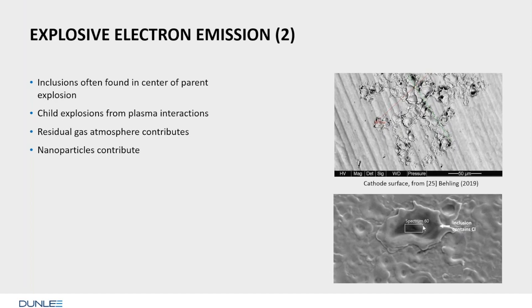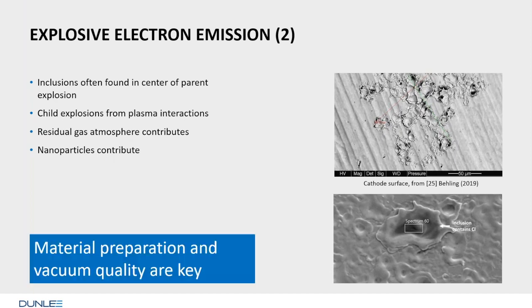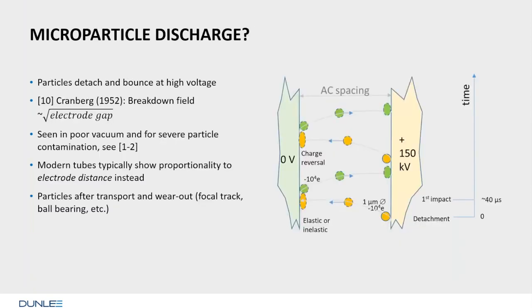So this is not good because it is a chargeable inclusion here. So once we have a big discharge, it can expand into small ones. So you see often traces of discharges. And the residual gas atmosphere contributes, and also nanoparticles on these surfaces contribute once they are subject to ion bombardment. So material preparation and vacuum quality are really key to prevent this.